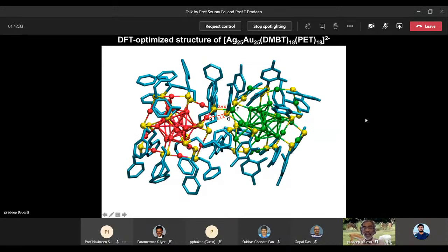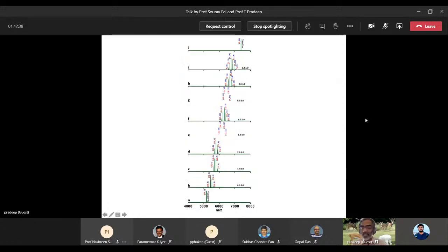Now, this peak is the one that results in all these other peaks, and we can today compute this dimer, and we can see that these interatomic distances are such that they are interacting, and atoms indeed exchange. Chemists, of course, can do many more interesting things. We can start with Ag25 and add a little bit of Au25 to it. And I told you before that an equilibrium distribution occurs. All these gold atoms essentially end up getting substituted. Now, this is favored, as I told you.